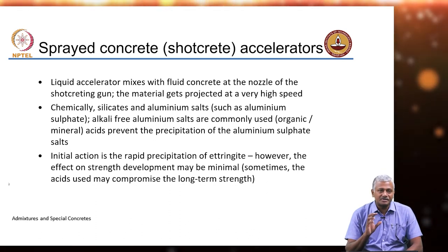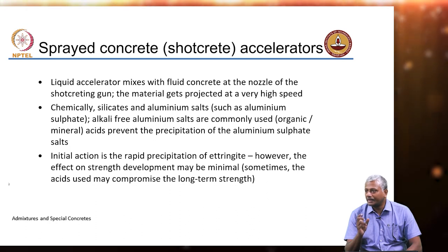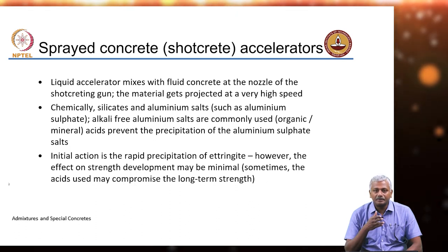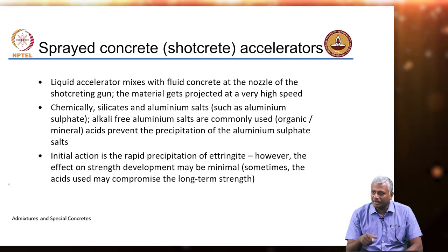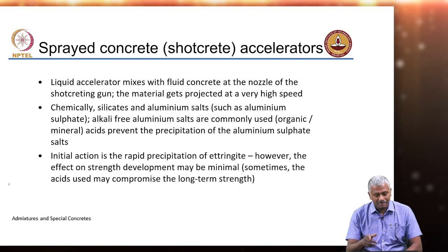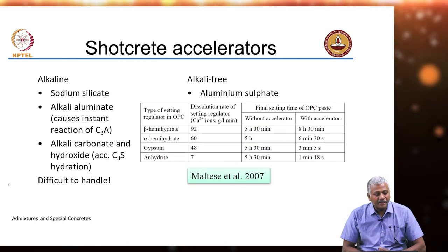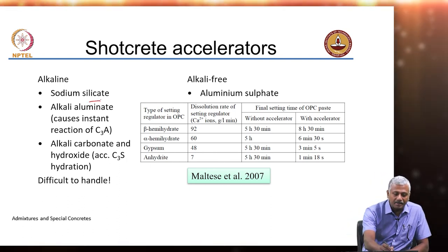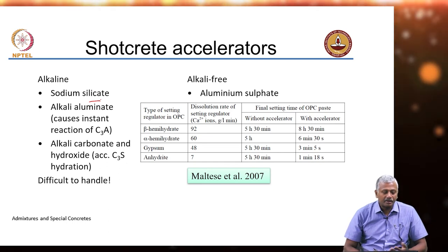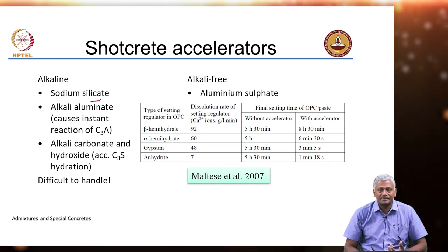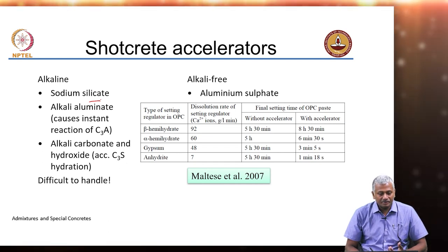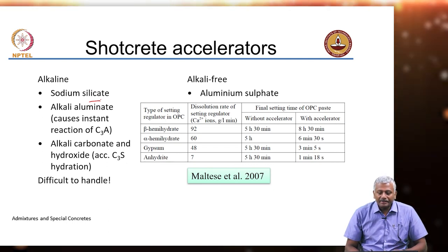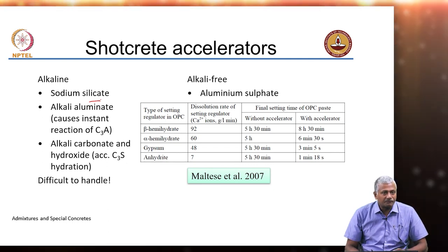All of this has to be carefully studied before implementing in concrete. Alkali free accelerators have now started making inroads into concrete in a much larger fashion because of the advent of 3D printed concrete. That is something we will talk about when we get to 3D printing separately. Just to give you some chemistry of these accelerators, you have alkaline accelerators like sodium silicate, alkali aluminate, and alkali carbonate and hydroxide. These are difficult to handle because they have very high pH levels, it can be extremely caustic. On the other hand, the alkali free accelerators like aluminum sulphate are quite useful.